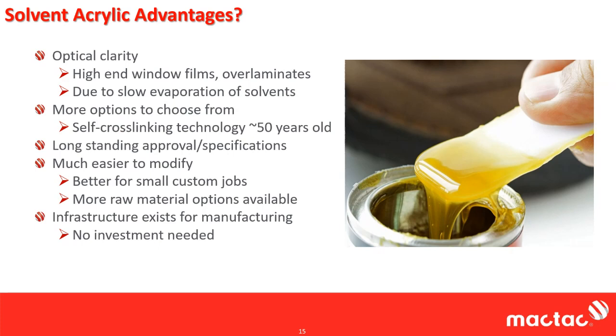And there's a lot more raw material options for solvent-based adhesives than the UVs. Again, a lot of the chemical companies, they're seeing the UV become more and more prevalent. They're making more and more raw material additives for UV. There's not as many to select from right now. The main problem here is they got to be heat stable and they can't interfere with the UV cure. So if you're going to put in a tackifier that absorbs UV light, well, you're not going to cure your adhesive, and everything I said about cross-linking kind of goes out the window. And that's kind of the challenge there.